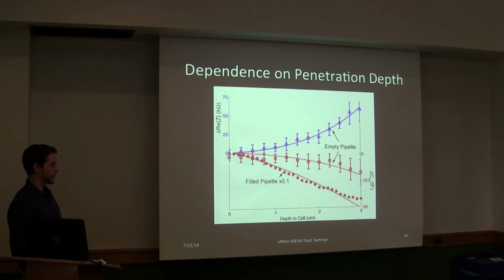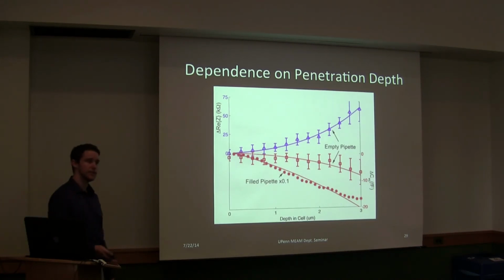Also, at the nanoelectrode scale, the pipettes are much more sensitive, and so we can actually look at the dependence on penetration depth. So here we had a CNP that we programmed to traverse downward at a constant rate, and we measured these signals again, the real part of the impedance change and the capacitance change. And we can fit this with a circuit model, and it's basically a monotonic dependence.